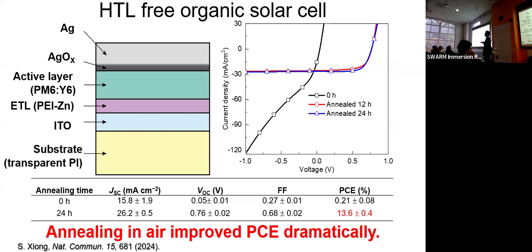But after annealing the devices in ambient air for 24 hours, the performance improved dramatically from 0.2 to around 14%. This dramatic improvement could be observed because of the generated silver oxide interfaces.